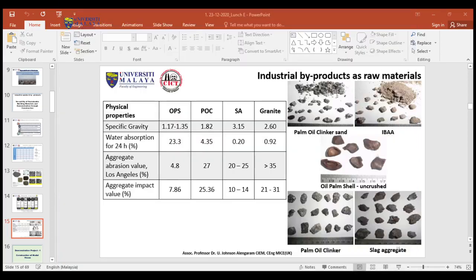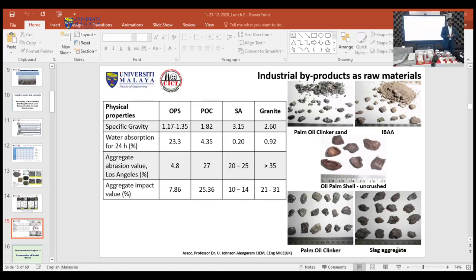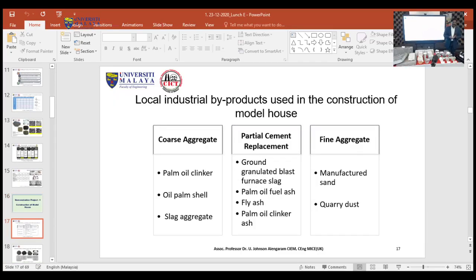In this project, we have utilized some of these local industrial byproducts and waste materials. For the replacement of batu, coarse aggregates, we have used palm oil clinker, oil palm shell, and the slag aggregate from the steel industry. And also, as a partial replacement of cement, we have used palm oil clinker ash, fly ash, palm oil fuel ash, and ground granulated blast furnace slag for the pavements. And for the fine aggregates, we have used manufactured sand, which is, as I mentioned, processed from the quarry dust.